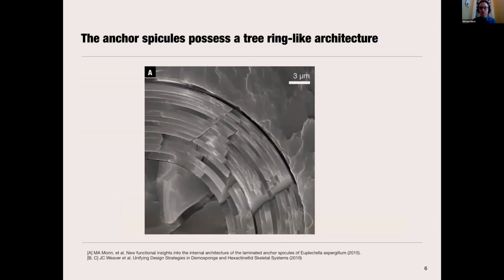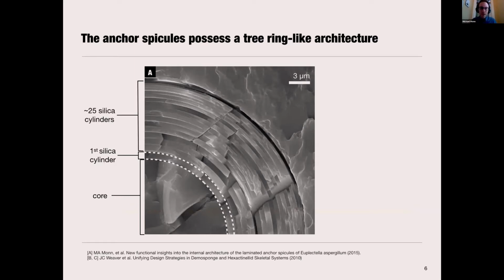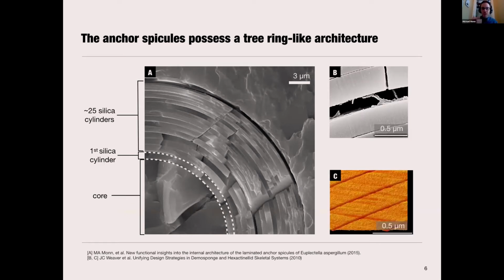So taking a closer look at this tree ring-like architecture, we can see that it consists of a central core that's about 20 microns in diameter, and then a number of silica cylinders. While they look fragmented, like they might be sections of a cylinder, that's just due to the process that we have to saw the spicules in order to see this cross-section. The cylinders are actually intact, and there are about 25 of them in each spicule. And you can see if you take even a deeper look, this was some work by James Weaver at Harvard, which I collaborated with a couple of years ago on a paper. He looked specifically at this proteinaceous layer, which you can see in subfigure B, a fibril that's spanning two separated silica cylinders.